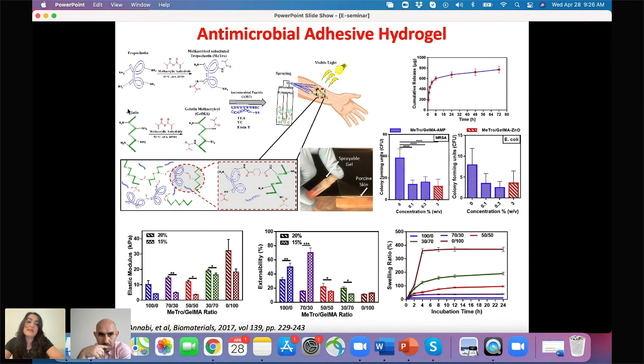Basically, by changing the concentration or the ratio of tropoelastin and gelatin, you can change all the physical properties of the hydrogel as expected. By increasing tropoelastin, you can increase the elasticity or extensibility of the hydrogel. By adding more gelatin, you can make the hydrogel stiffer. You can also play around with the degree of swelling and degradation rate of this biomaterial. Therefore, based on the final application, you can tune these properties and use it for a wide range of applications in tissue engineering.